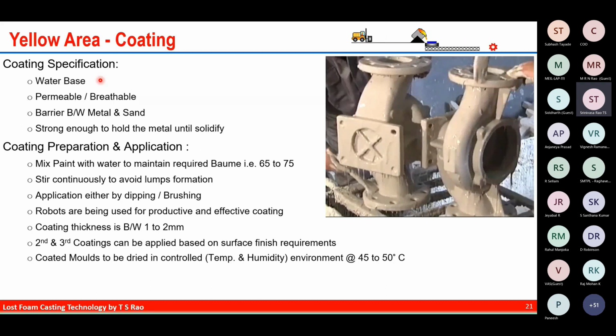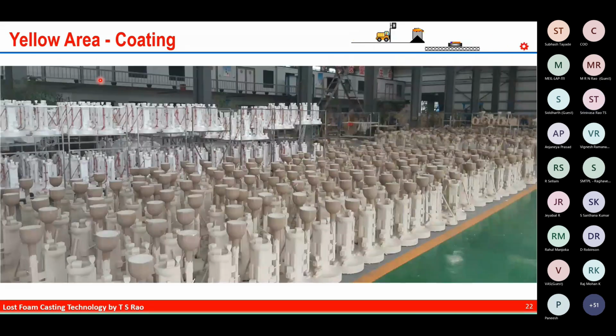And in some cases, second and third coating also can be applied, depends on the surface finish and quality requirements of the casting. And coated molds again move to the controlled drying rooms in controlled temperature and humidity at 45 to 50 degrees centigrade. After this, you can see a foundry in China with lot of the foams. These are glued and these are coated.